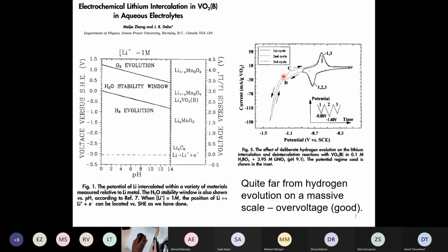For example, if you think about it, the lead acid battery operates at 2 volts, and it should have no right to do so because the water stability window is only about 1.2 volts wide. And you'll learn later on from Chong Yin that you can extend the water stability window to be 3 volts and even greater. So it's kind of interesting that this sort of thing happens. So anyway, this sort of convinced us that we are far enough away from the hydrogen evolution reaction that the vanadium oxide electrode should be okay.